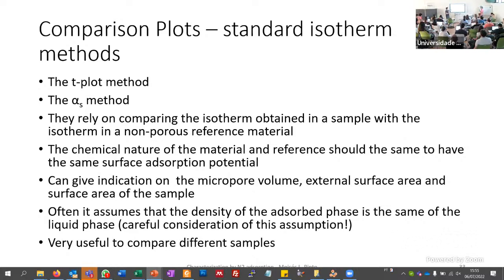It can give you an indication of the micropore volume, the external surface area, and also the surface area of the sample. And we are going to use also these values to compare with values that we are going to obtain from other approaches using the crystal structure. So often we assume the density of the adsorbed phase. You need to assume it, and usually you assume that the density of the liquid nitrogen is the same as your adsorbed phase.